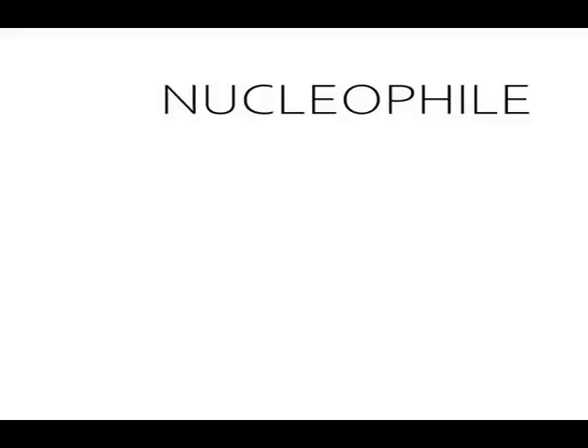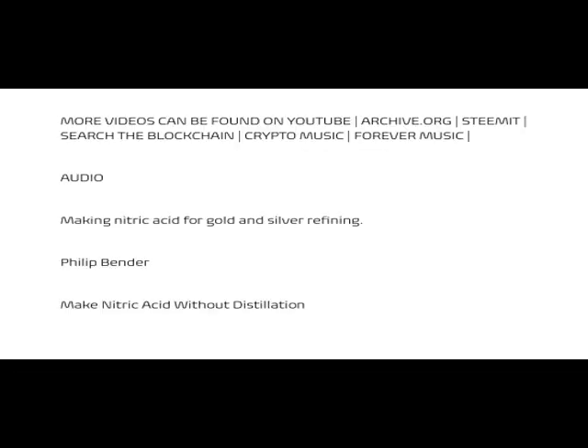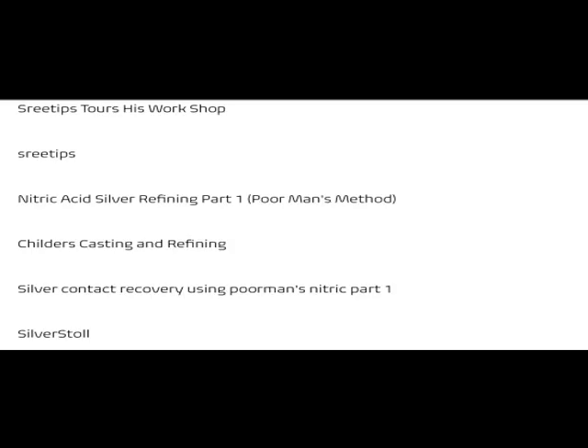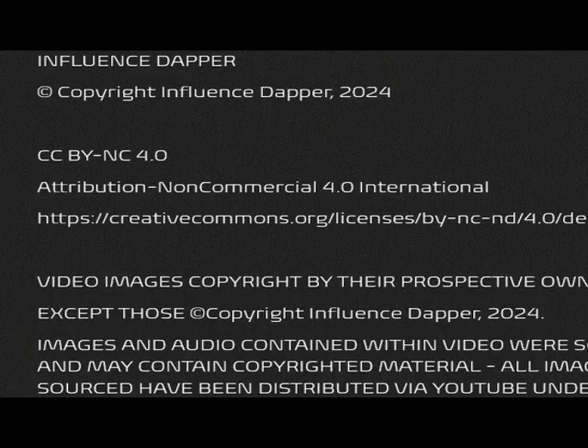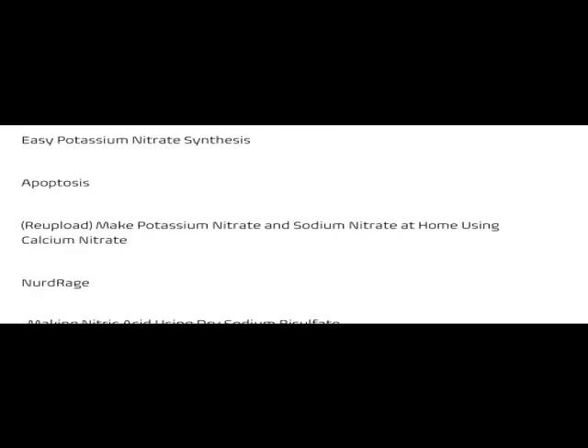While I'm sure they can be improved by adjusting the water added, it seems the dry method using 2 mole equivalents of sodium bisulfate is best. I'm actually quite surprised just how high the yield is. At around 95%, this is competitive with using sulfuric acid. Since sulfuric acid is somewhat valuable for the amateur, if you don't need pure nitric acid and can tolerate 75% concentration, then using very cheap and easy to acquire sodium bisulfate may be preferable. A minor bonus is that both reagents are